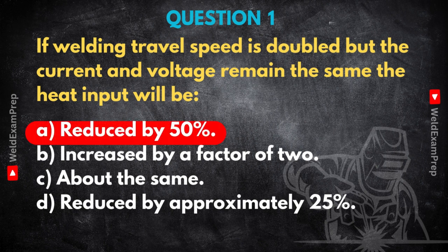Reduced by 50%. My first thought might be, faster speed maybe spreads the heat thinner, but is it always that exact 50%? Well, theoretically, yes. The formula for heat input essentially is energy per unit length. It's calculated as voltage times amps times 60, divided by the travel speed, usually in millimeters per minute. So if voltage and amperage, that's your power, stay constant, and you double the speed in the denominator, mathematically, the result is halved. So it's an inverse relationship. Double the speed, half the heat input per millimeter or per inch of weld.